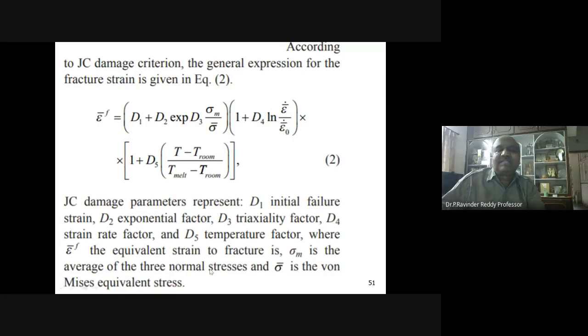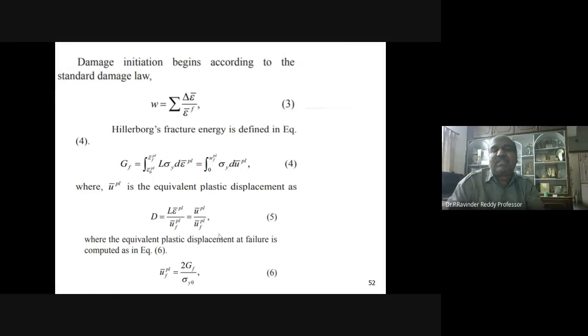And the coefficients here again, when you go for the strain rate for fracture, when damage mechanics is associated, we have parameters like D1, D2, D3, D4, which are the constants for these models available. When you select that model, these constants will automatically be given. And we can calculate the deformation in terms of strain rate and fracture, the damage, because when the chip is separating, we are going to calculate the damage mechanics. So we use Hillerborg's fracture energy. This is the strain energy release rate. We will calculate for the slope of the same, the yield strength and the strain rate in the plastic zone.